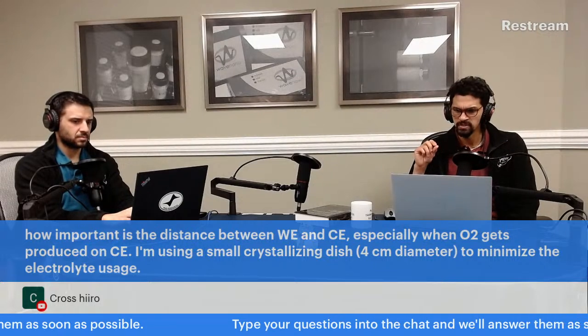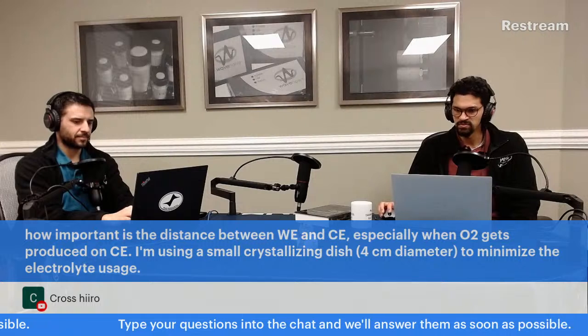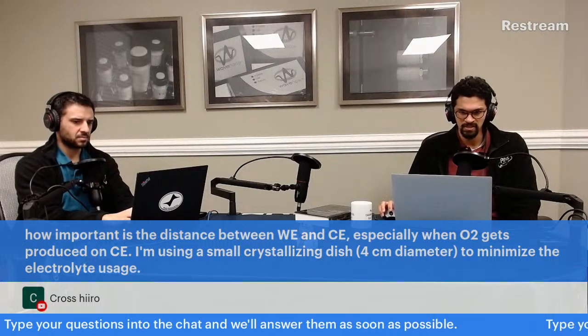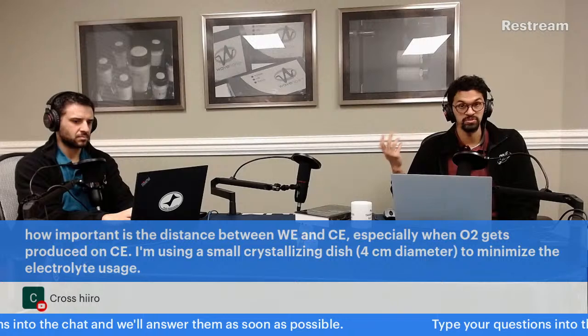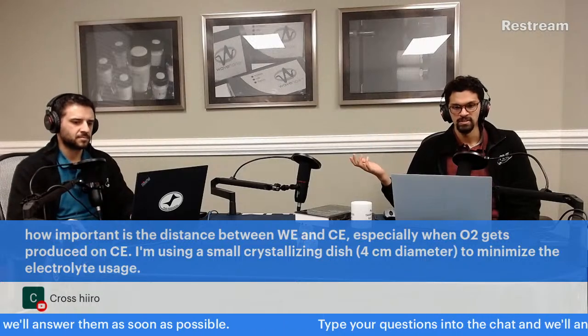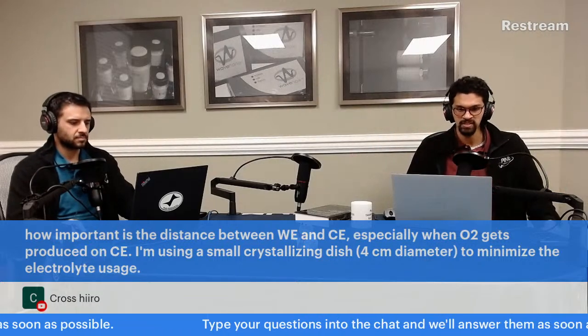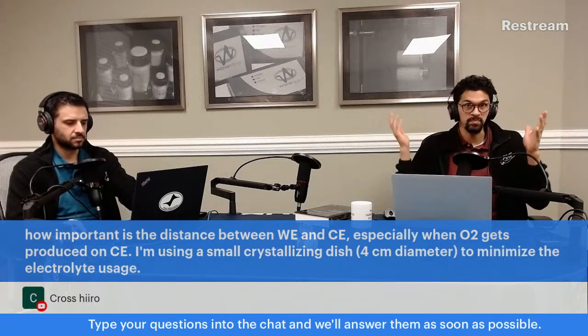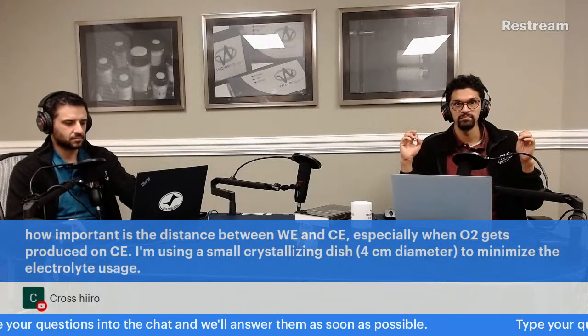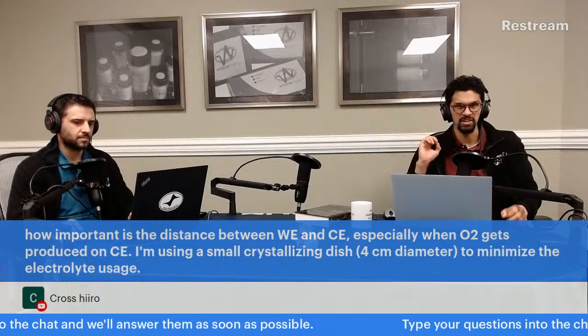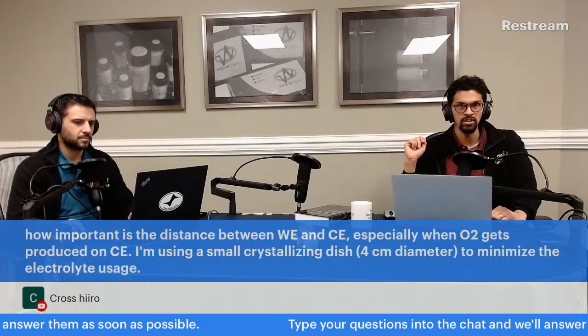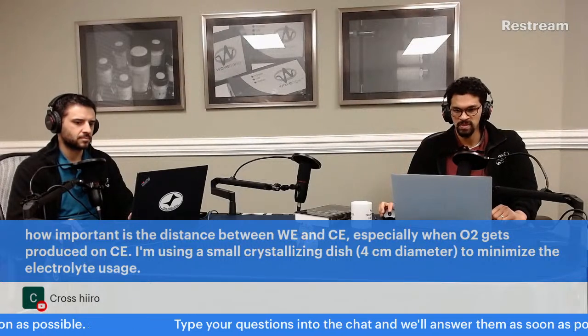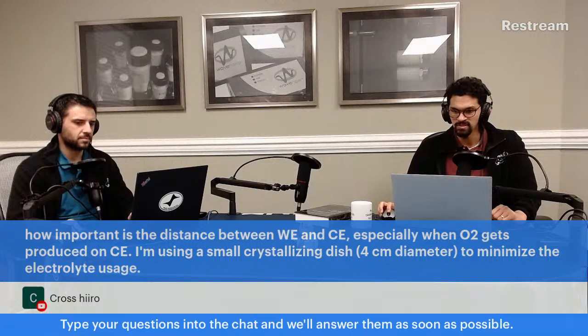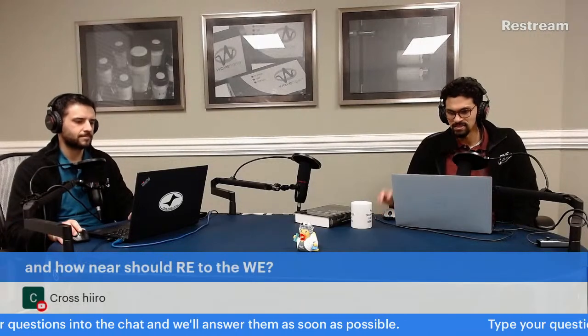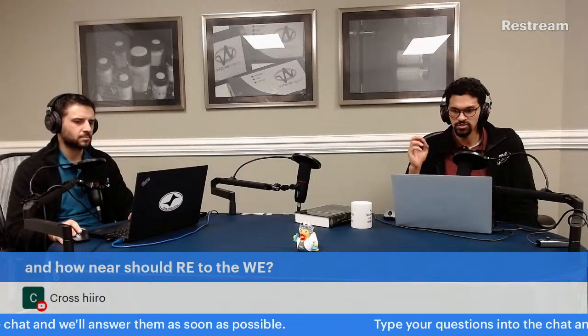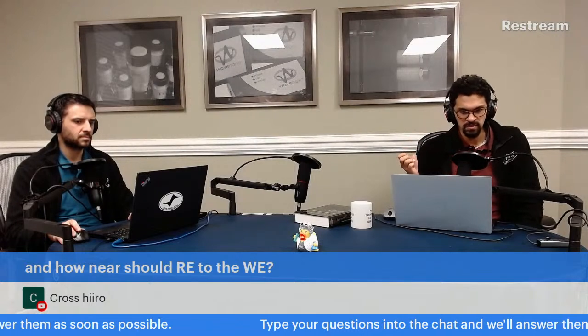But if you are worried about, say, oxygen that's produced on the counter electrode affecting things that are happening on your working electrode, then yeah, you can separate them in such a way, as far as you need. But it's that resistance between the counter and working that becomes important, problematic. And then lastly, how near should the reference electrode be to the working electrode?